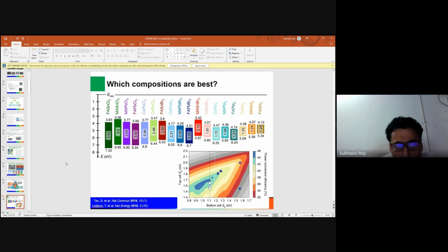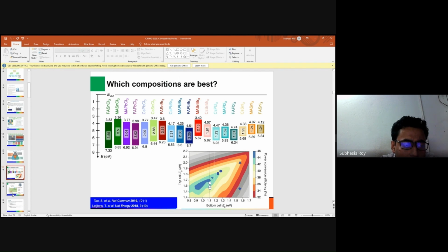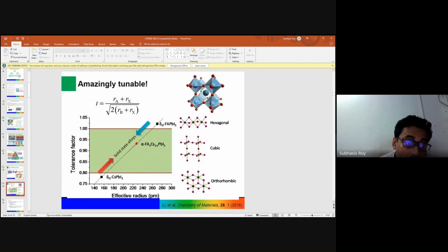Now, if you want to select the perovskite material, note that perovskite materials are already applied for solar cell fabrication, but are still not commercialized because of some problems: they degrade with time, some introduce toxic material, and in some cases they absorb moisture from the air. So many problems are there. So when we are fabricating solar cells using the perovskite, we select the material from this structure with a proper band gap. Then we define the doping material, and then we fabricate the solar cells. And for the fabrication, we take the tolerance factor, because the tolerance factor is most important. If the T value is between 0.89 and 1, that means the material is stable. So that material we can apply for the solar cell fabrication process.